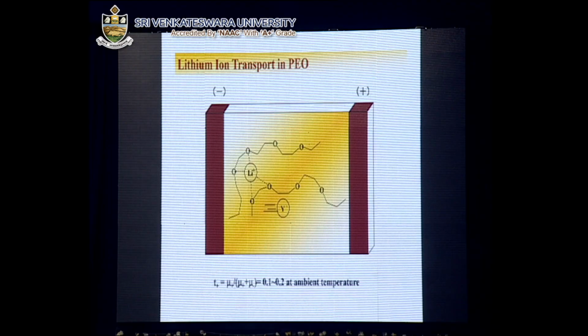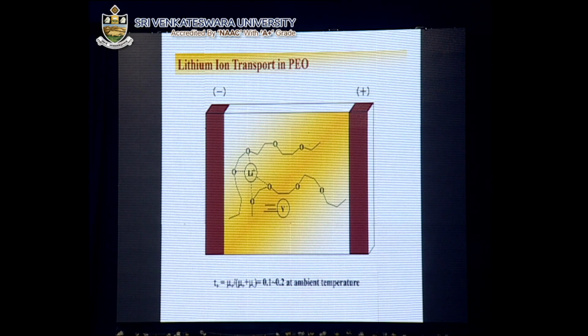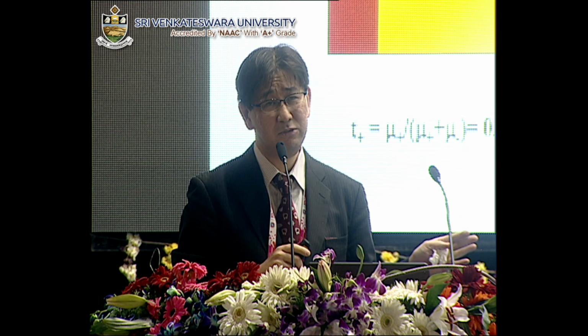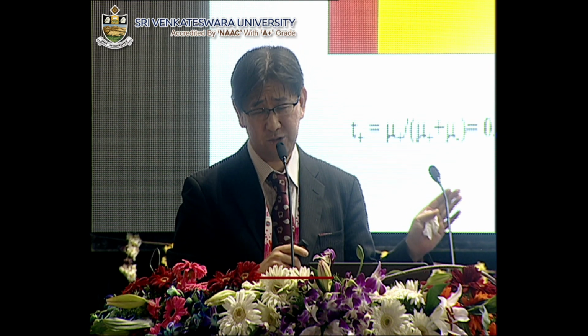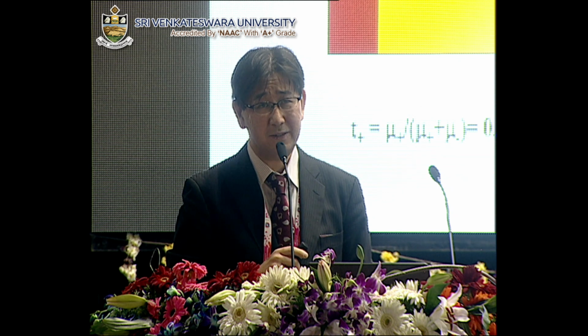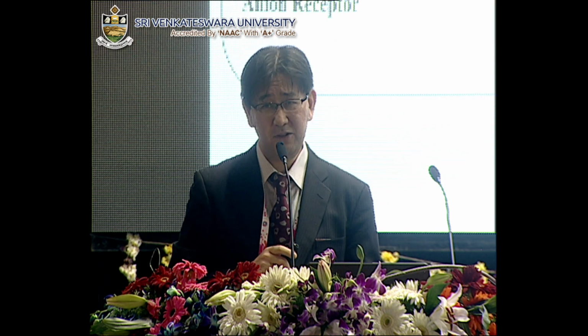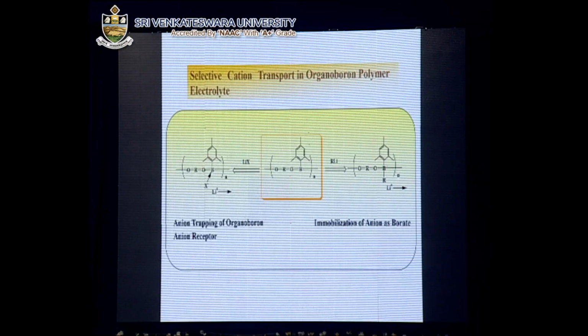And till now, as the most common solid polymer electrolytes, polyether derivatives have been so widely investigated. However, in spite of their moderate ionic conductivity, their lithium transference number, I mean the selectivity of lithium cation transport, is generally very low at ambient temperature due to the strong binding of ether oxygen to lithium cations. And as a result, generally the lithium transference number is only at most 0.1 or 0.2 at ambient temperatures. So we developed an idea that boron incorporation into the polymer should be an attractive, promising approach to enhance the selectivity for lithium cation transport.